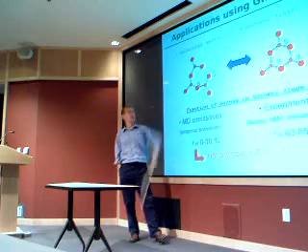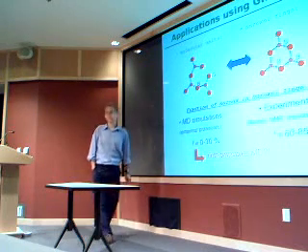Doing the straight molecular dynamics gave these f values which were very small, but there was a person in Japan who came with a biased way of doing molecular dynamics, and he gave us molecular dynamics samples which had a high fraction of these rings, like the experiment says. So if we do these simulations straight, we get this, but he biased it so that he got this sample. And when we did the first principles molecular dynamics and the stability analysis, we saw that this is more stable. And that's the origin, in our opinion, of this controversy between the two.